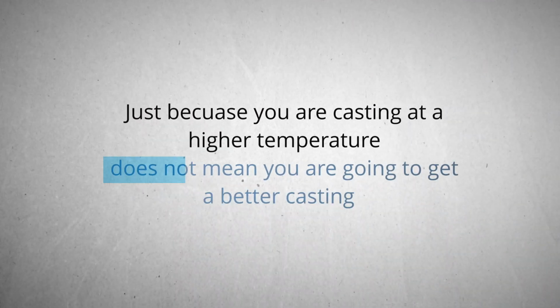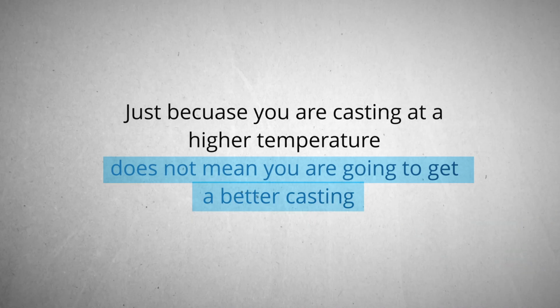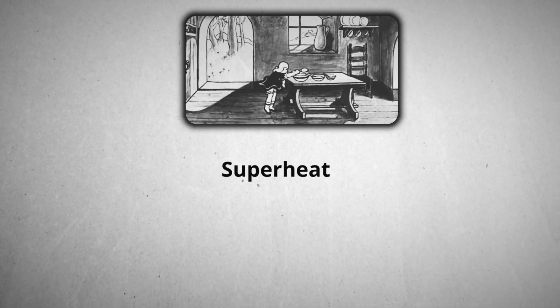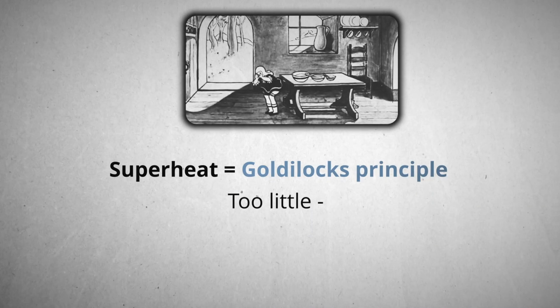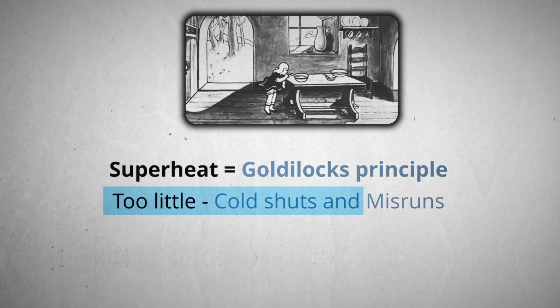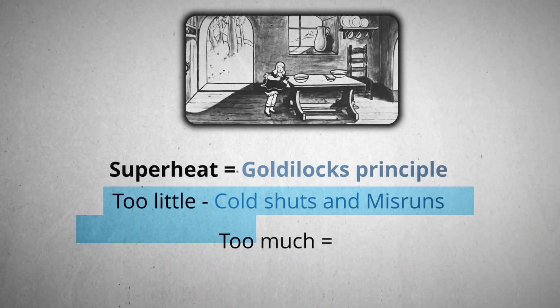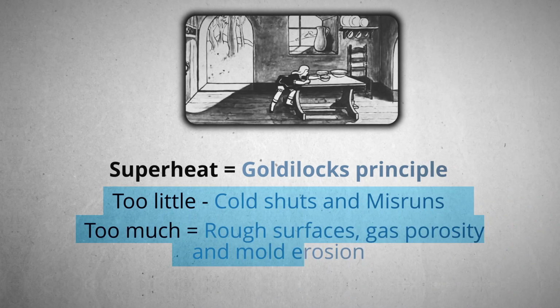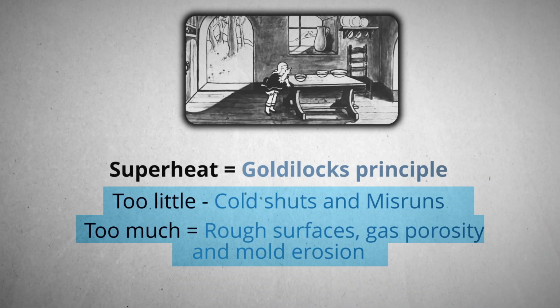But remember, just because you're casting at a higher temperature doesn't mean that you're going to get a better casting. Someone once said, superheat is like the Goldilocks principle to casting. Too little, you're going to run into cold shuts and misruns. Too much heat, you're going to run into rough surfaces, gas porosity, and possibly mold erosion. So just at the right temperature, when that porridge is just right, you are going to get a better casting.